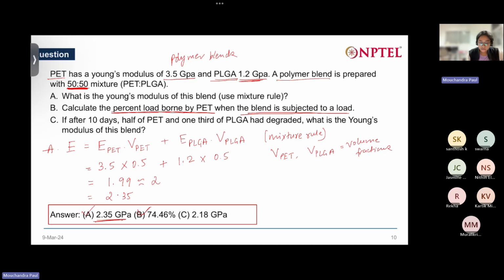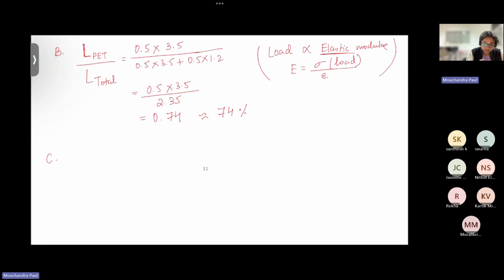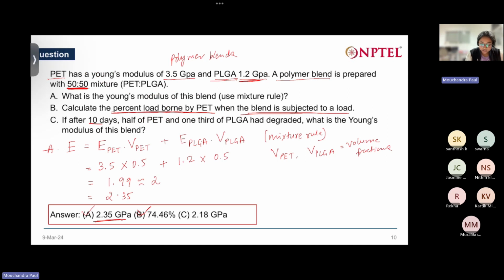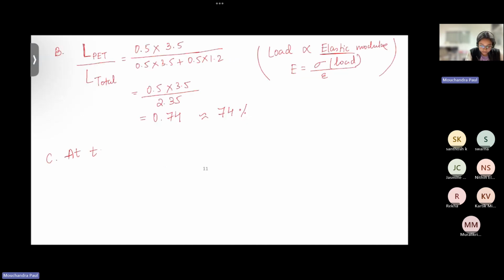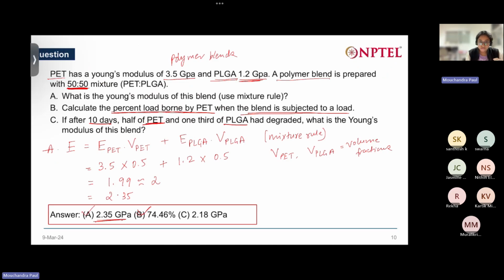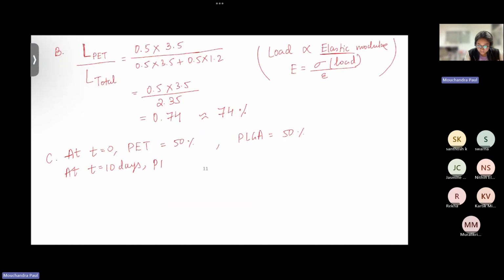Okay. And now the C part. What is C part? It is saying that after 10 days, half of the PET and one third of PLGA has degraded. Now, what will be the Young's modulus of this blend? So, if you write the problem now like this, at T0, PET consisted of 50% of the total volume, whereas PLGA consisted of the other 50%. Now, after 10 days, T is equal to 10 days, you found what? You found half of the PET is gone. So remaining half is left. So after 10 days, PET is 25%. So half of 50%, 25% is left with you.